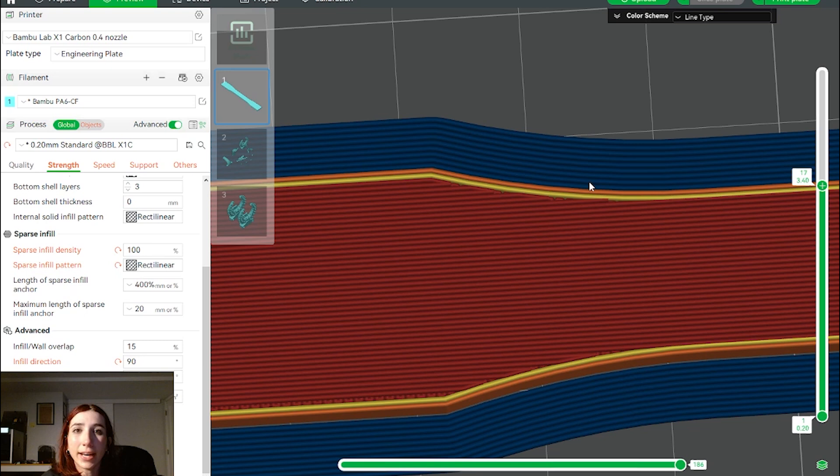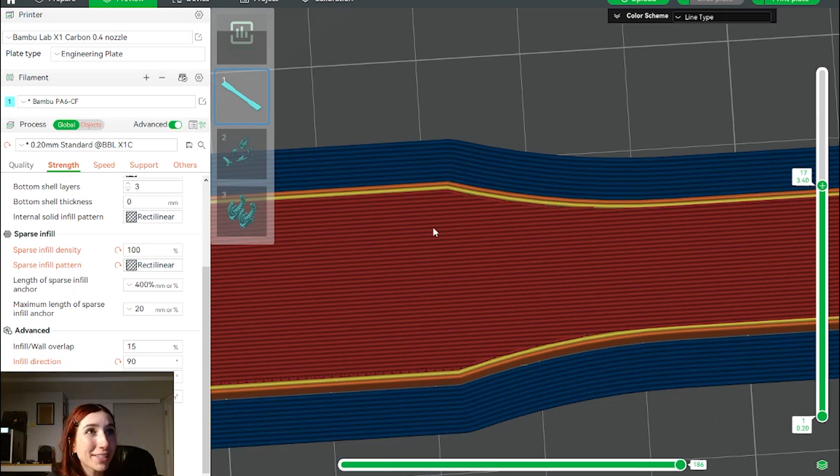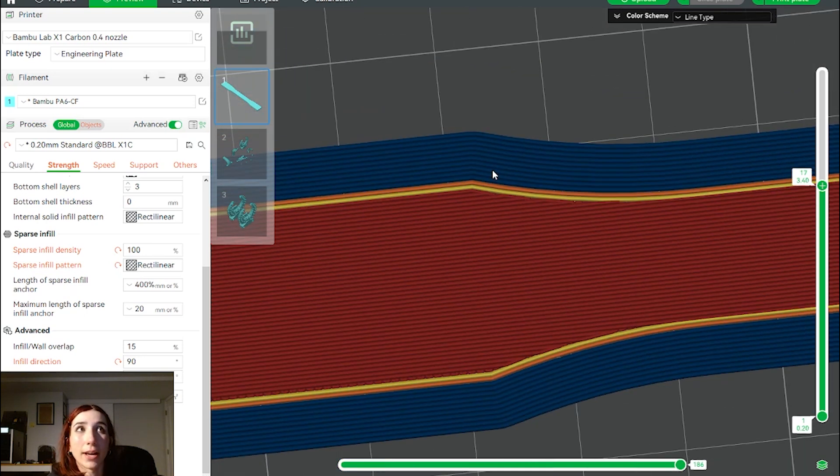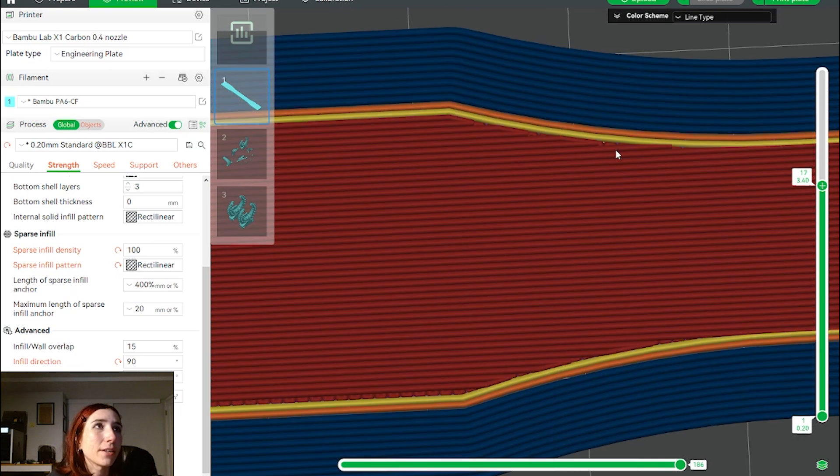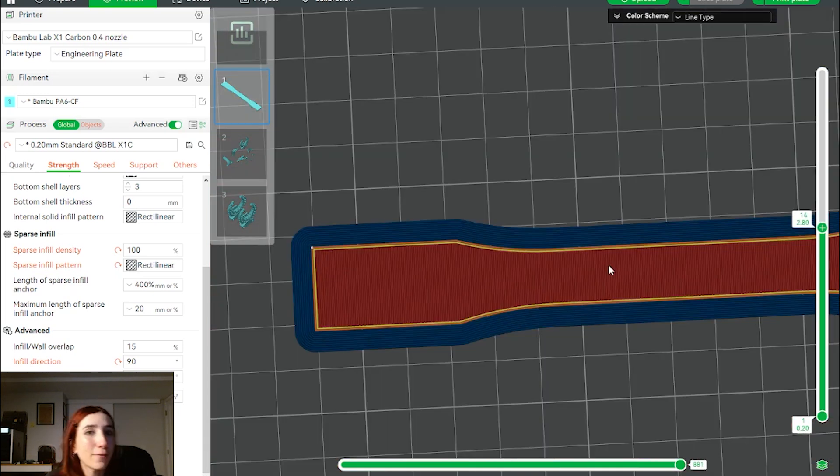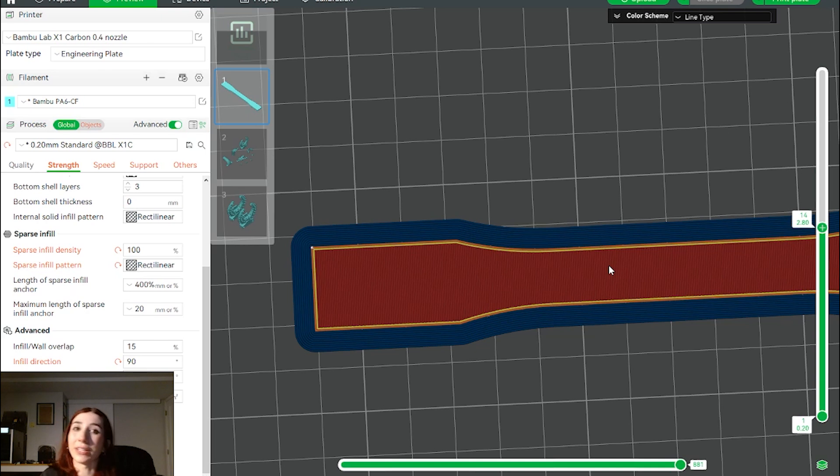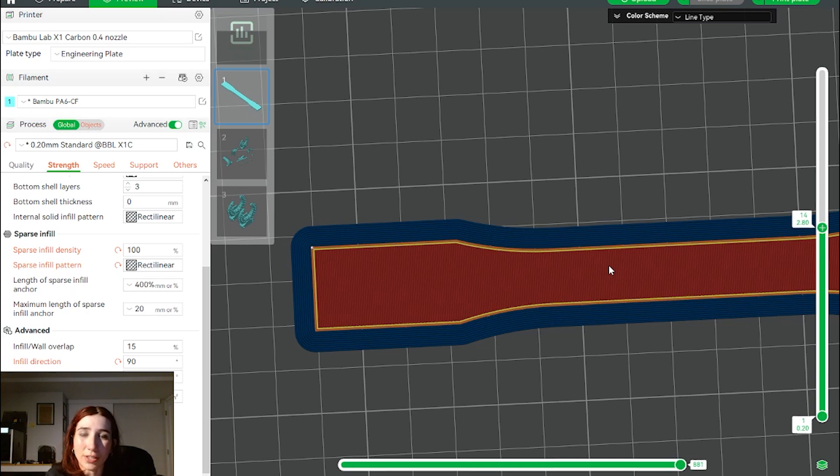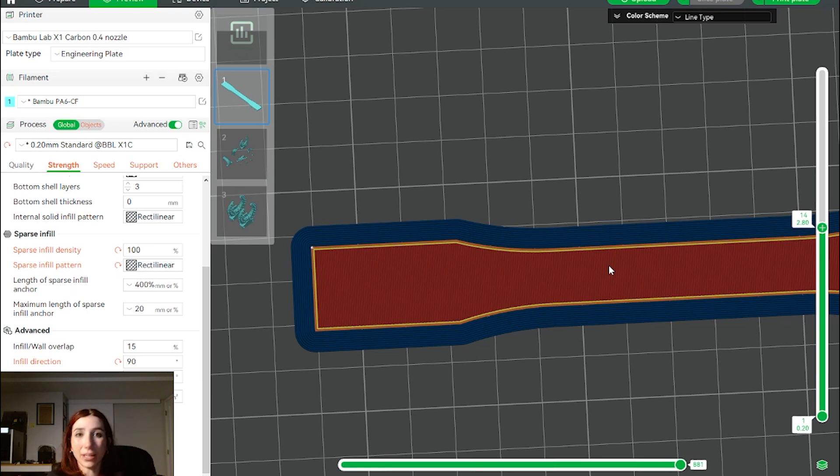From looking at this toolpath, I can evidently conclude that the reason why we had a failure site here was because of these void structures. If all five of my tests failed in the same region outside of the gauge length, I can conclude for the most part that it was due to the toolpath. But I can't conclude any tangible stress strain data from the data I collected from this sample because it's an inconclusive test. I can't use the data it failed in an undesirable region.